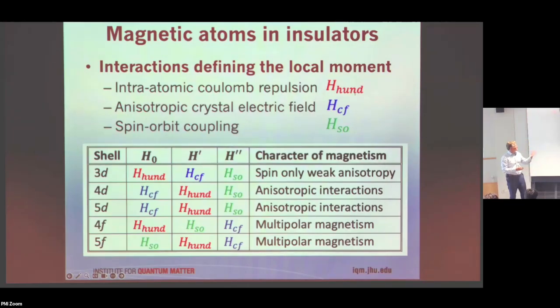Now, the model systems in this case turn out to be rare earth based. And so I just want to remind about the different character of magnetism in insulating materials, ordered by the shell which is generating magnetism. 3D was what we were talking about, but a very special case where there was an orbital degree of freedom left and spin-orbit coupling, and it became very anisotropic. But in many cases, if you think about copper, for example, or nickel, it can be fairly isotropic, and so it's really dominated by the intra-atomic repulsion and crystal electric field effects.